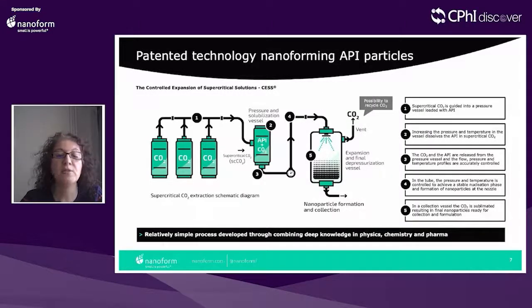We do this using our patented technology called CESS, which stands for Controlled Expansion of Supercritical Solutions. I will show you briefly the principles behind this technology and the different steps. We use supercritical CO2 as a solvent, which is inputted into a solvation vessel where the API is located, and by controlling pressure and temperature, we can solubilize the API. The solution is driven through a series of tubings, which represent a controllable thermodynamic pathway. During this pathway, we can induce nucleation and particle formation by controlling process parameters. The particles will first nucleate and then grow, and will pass through a nozzle, which will allow them to be released from the solution through expansion.